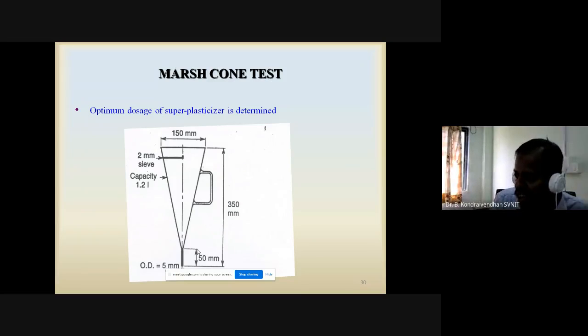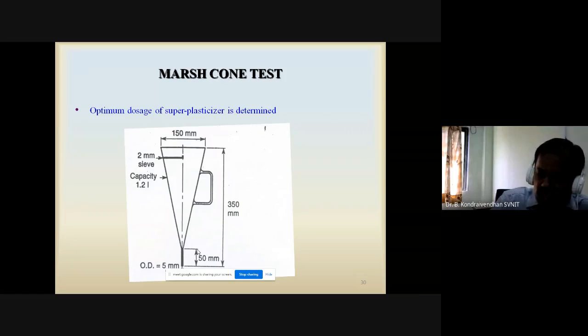So we have to start your stopwatch, and you have to measure every 200 ml of paste passing through this 5 mm diameter nozzle. What is the time taken? You have to measure it. You have to start the dosages from the lowest dosage, like let's say 0.25, 0.5, 0.75, like that. Gradually you can increase the dosage, and you have to measure the time taken. If you keep increasing the dosage, the time will become quicker.